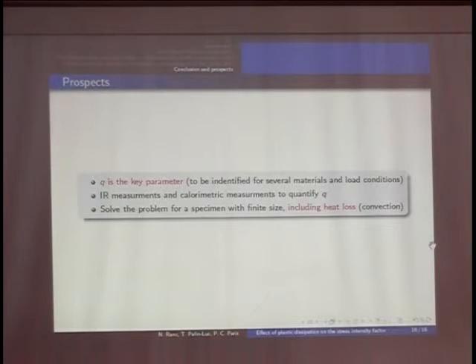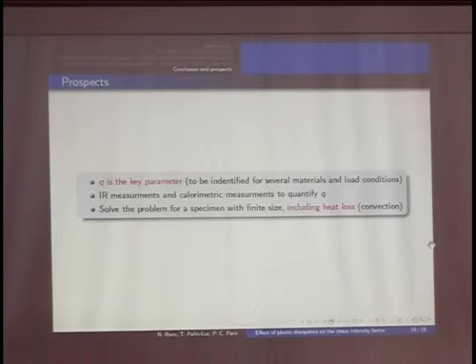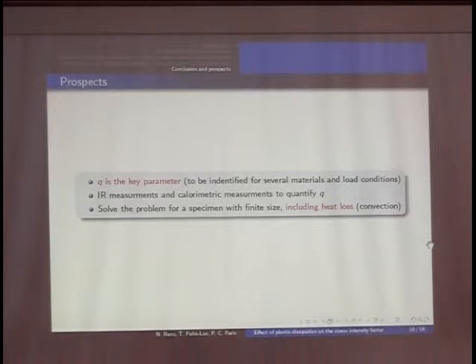effects, like also these thermoelastic effects, because in this higher ratio they also cause a certain irreversibility, because different grains get different elastic stresses and therefore different heating and cooling, and therefore you have a certain loss. This also makes a heating, and in a magnetic material, the Bloch walls, the movement also makes heating. But these are really small.